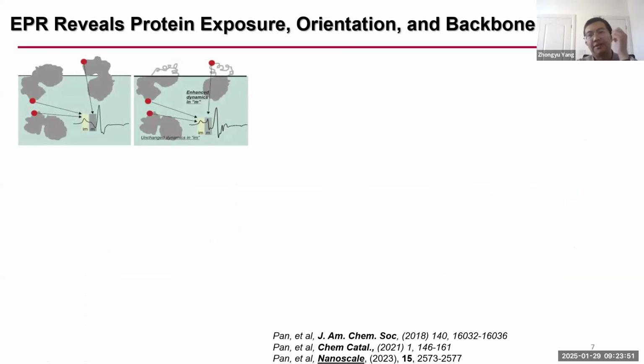Now, to understand or to review the exposure area and orientation on the surface, we use spin labeling and EPR. And the idea is quite simple. If a labeled site is buried, you see highly restricted motion, which we call the immobile peak. If the labeled area is exposed, then we see a mobile peak, meaning they have a very distinctive rate and order in their motion, and we proved that in simulations. We also use an interesting finding that urea does not unfold the proteins buried inside the MOF, but only unfolds the proteins exposed.